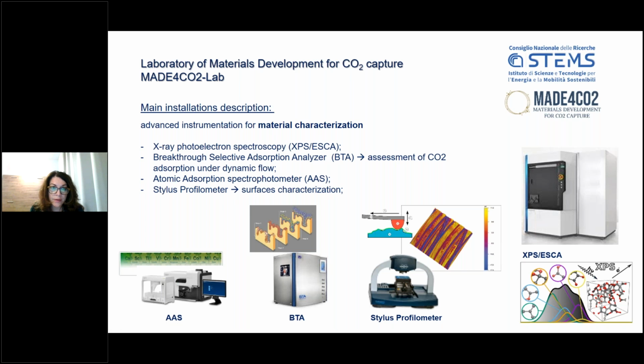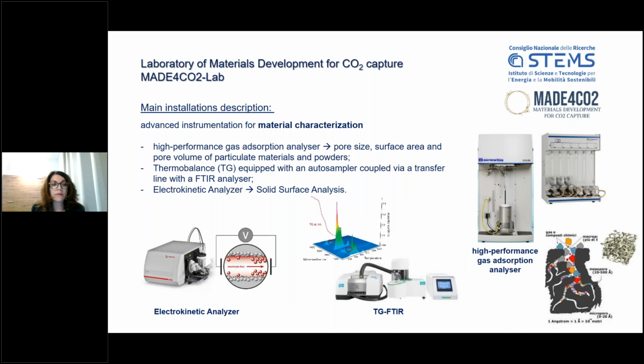The breakthrough selective adsorption analyzer to obtain the assessment of CO₂ performances of the solids under dynamic flow, so under very realistic situation and conditions. An atomic adsorption spectrophotometer that will be aimed at the characterization of the material in terms of elemental composition. A stylus profilometer for the surface characterization, and of course a high performance gas adsorption analyzer to obtain a clear picture of the pore size, surface area, and pore volume of the materials and powders.